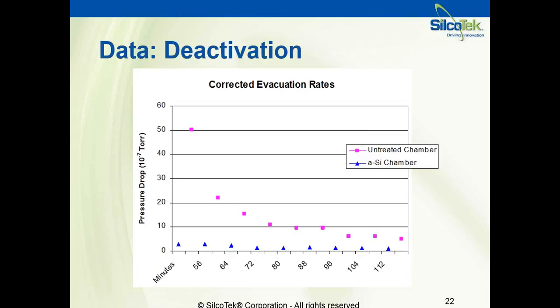In the blue triangles, you see simply an amorphous silicon coated chamber, coated with our Silicoid coating. And you can see that the same pump down rate, the same pressure, is achieved in 30 minutes or less with the coated substrate. So this just results in much less outgassing, very low moisture absorption, and overall a lot faster pump downs, much more efficient, much more friendly to a production environment than a bare substrate.